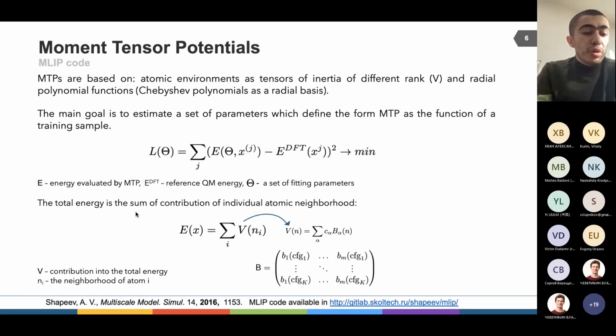We employ the moment tensor potentials as a model for approximation of density functional theory calculated energy. MTPs, moment tensor potentials, are based on a representation of atomic environments as a tensor of inertia of different ranks, in practice usually fifth rank, multiplying by a radial polynomial function. And the main goal is to estimate the set of parameters which define the form of the moment tensor potential as a function of the training set. The training of the MTPs can be done by solving the minimization problem.